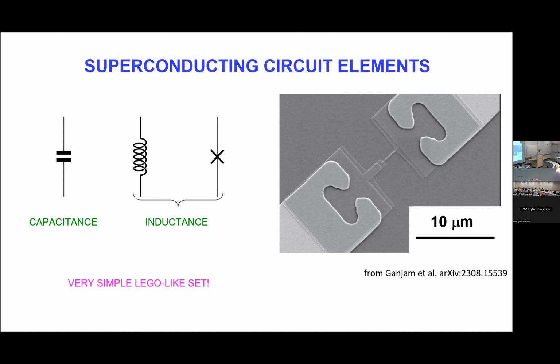So there are three advantages. First of all, the superconductivity itself, the pairing of electrons in aluminum, completely follows BCS theory. So you know exactly the kind of pairs you have. There's a very large coherence length in aluminum. The pairs are very big, so they average over a lot of impurities. That's an excellent thing. The transition temperature is low, only 1 Kelvin, but that's correlated completely to the size of Cooper pairs. So you benefit a lot from very large Cooper pairs. Laura, who has worked on high-Tc superconductors, can confirm that it's not so easy to have a superconductor with a very short coherence length.